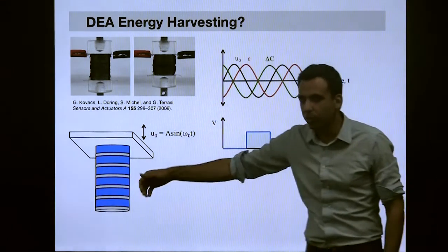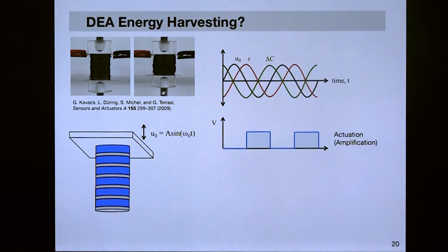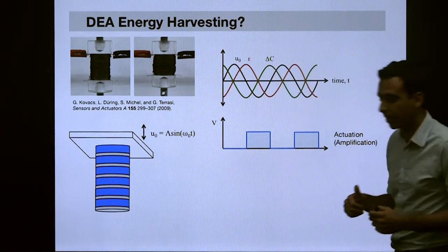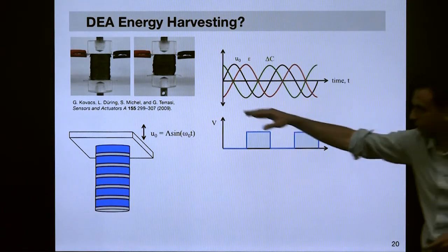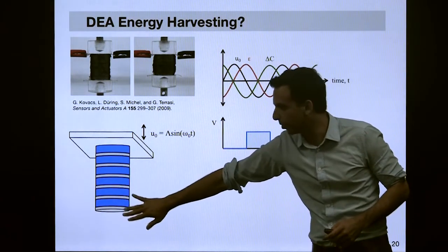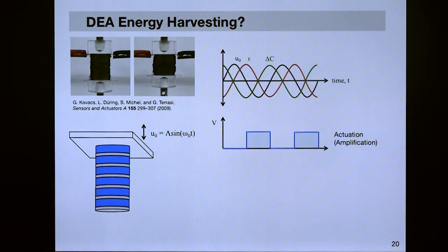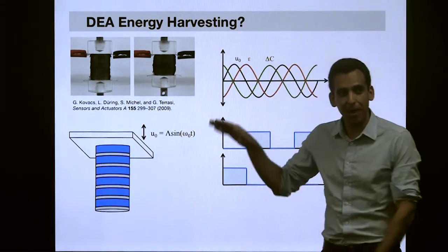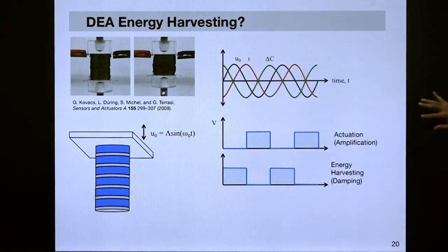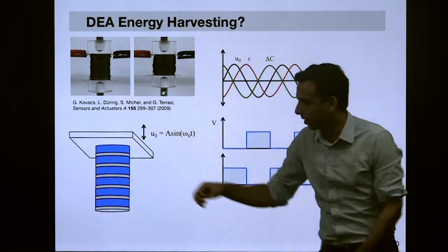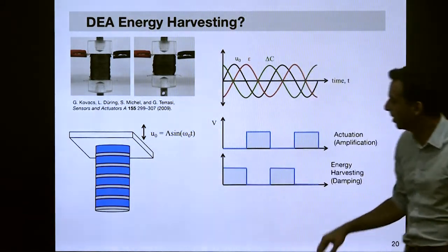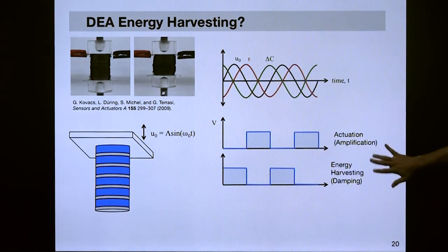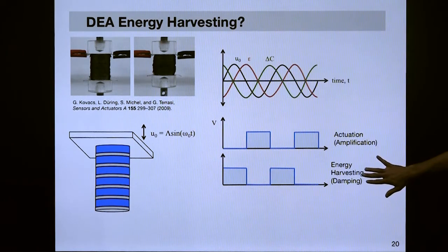So in addition to all the inertial forces leading to compression, we now also have those Maxwell stresses, and that leads to amplification and an even larger amplitude at the tip. That would be an actuator mode. Alternatively, as it's stretching, that's when we apply electrostatic loading to the capacitors. Basically, we apply a compressive stress to resist or counteract that tensile motion, that elongation, and in that mode we're introducing electrostatic damping.